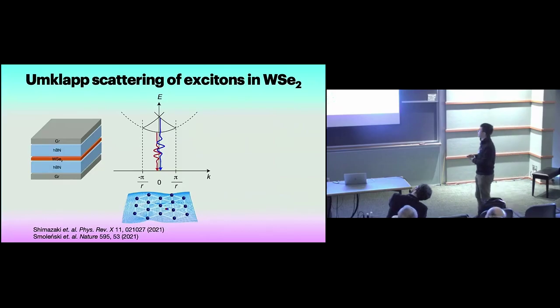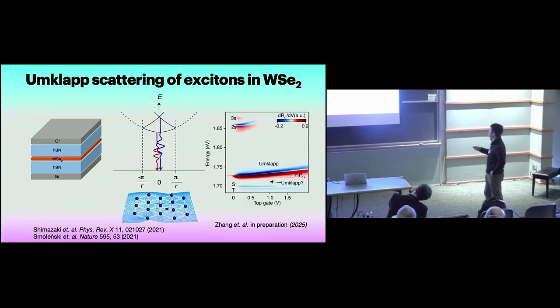What's nice about this is that I can just change the density of the electrons in the system and change the interparticle distance, change the size of the Brillouin zone. So if I apply a voltage and change the density, as I increase the density, there is this repulsive polaron branch which dominates the spectral response, and also two additional attractive polarons coming from the spin singlet and the spin triplet exciton binding to some charges. However, in addition to these main features, there is an additional peak showing up over here that corresponds to the Umklapp scattering.